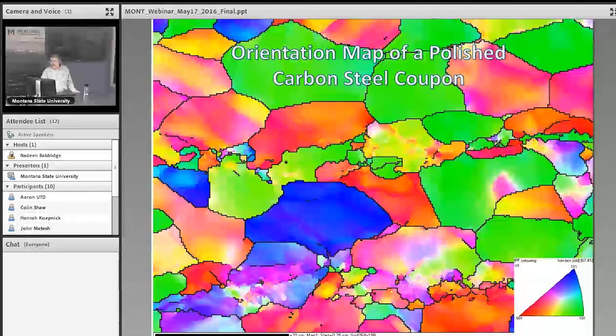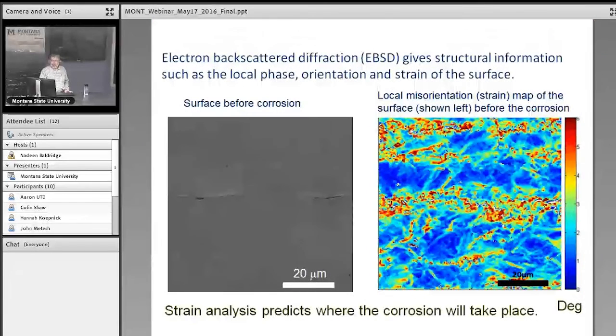Okay, so they are nice, pure orientations, but there are these areas that are not necessarily pure colors, like a rainbow. That's where the strain is. During the metallurgical processes, the lattice has been strained, the system didn't know which way to go, and we can actually map where the strain is by simply taking a derivative of this picture. When you do that, here is a polished surface before it is exposed to the environment. Here is the derivative. Everything that's red, blue, whatever, is an area that's strained. I can predict ahead of time that the system will corrode from these areas. I didn't have to do this corrosion experiment. Well, let's see if this was correct.